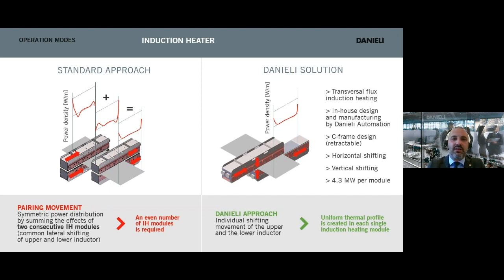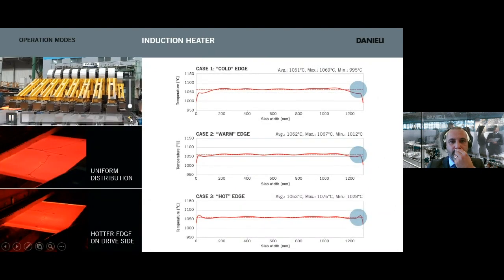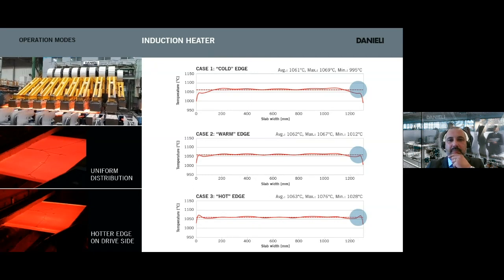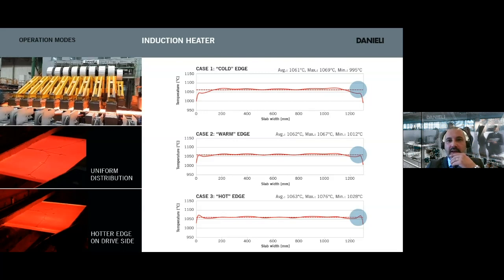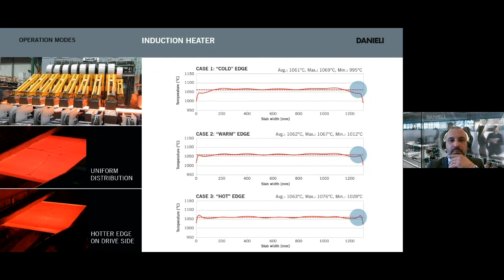In applying endless rolling, one of the most important pieces of equipment becomes the induction heating system, which at Danieli is fully developed, designed and manufactured in-house. And we are applying the latest technology of transversal flux induction heaters. The new generation allows both vertical and horizontal shifting, on which the horizontal shifting is utilized in order to optimize the temperature along the width. So we can select to get cold edge, warm edge, or hot edge according to the case. And the vertical shifting of each single module is made in order to grant, according to the changes in the transfer bar thickness, always the maximum efficiency of the flux transfer.